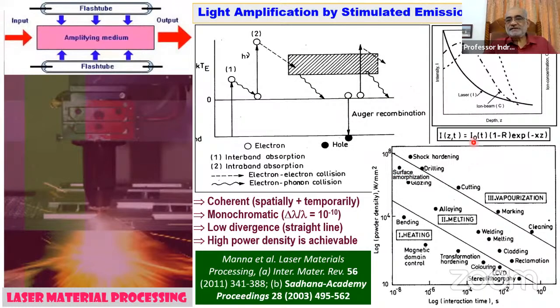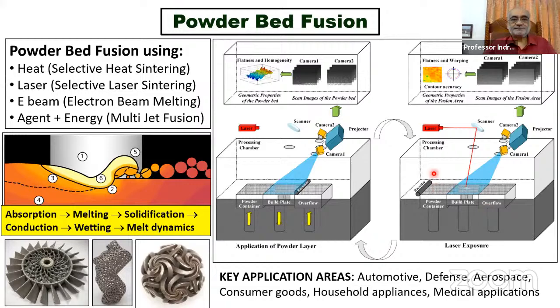And we know the other advantage is that the heating profile is exponentially decaying. So the heating zone is confined only to the near surface region, which could be just a few micrometers. And only two process parameters, the power density and interaction time, can actually allow me to go to heating, solid state, melting, vaporization, and in the process do all kinds of materials processing that one can think of.